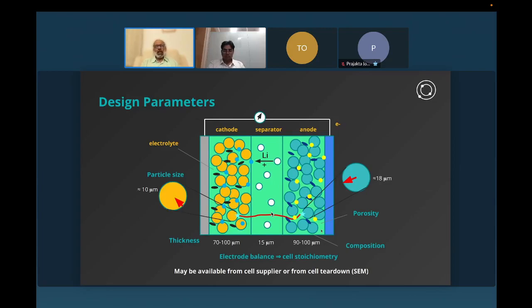And similarly, on the right-hand side, you need the particle size for the anode particle, and the porosity, which is the white space in between the particles on each electrode, needs to be known. These are known because when a cell manufacturer produces these cells, these are the set value. They target these values and they manufacture the electrodes, and hence the cell, with these numbers in mind. You also need to know the composition of each electrode.